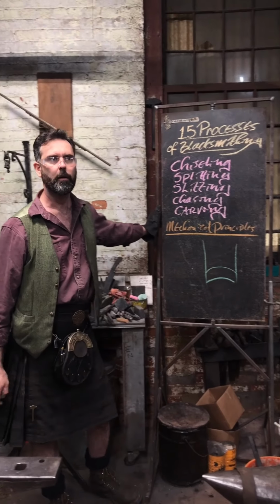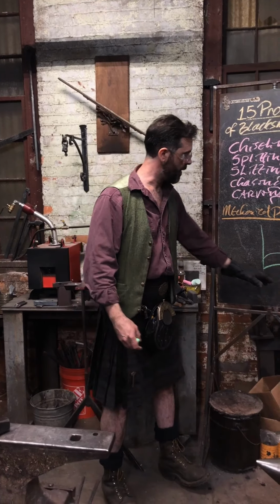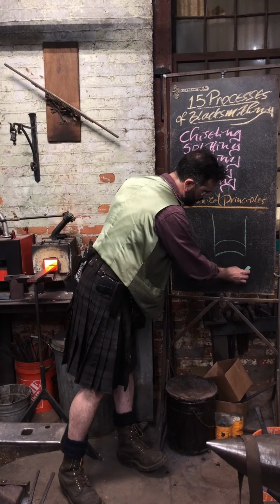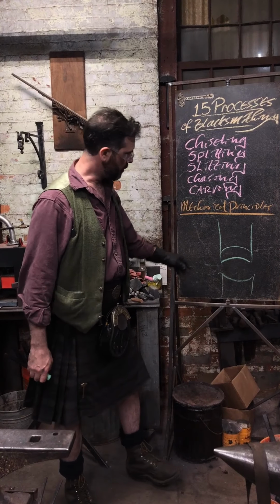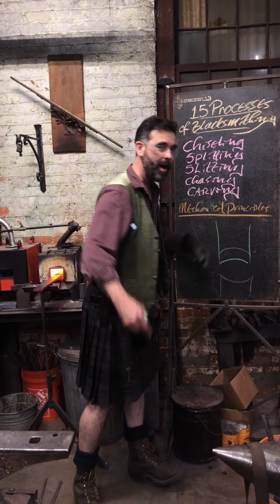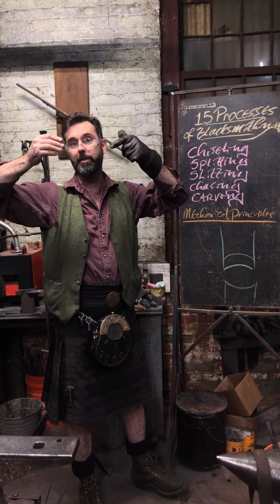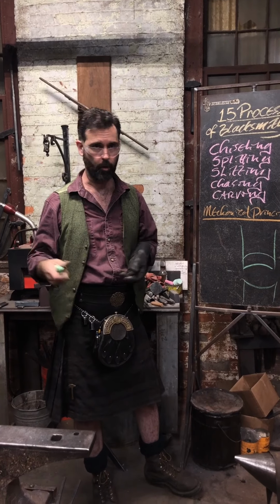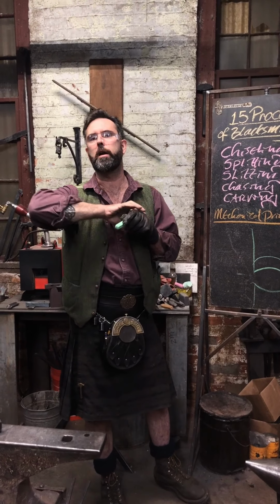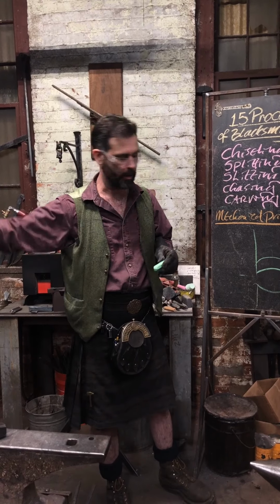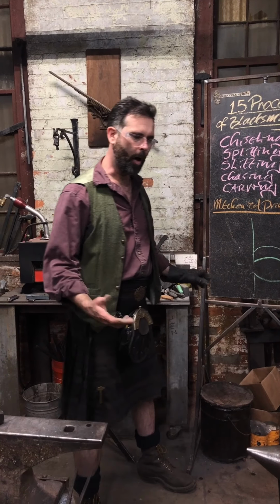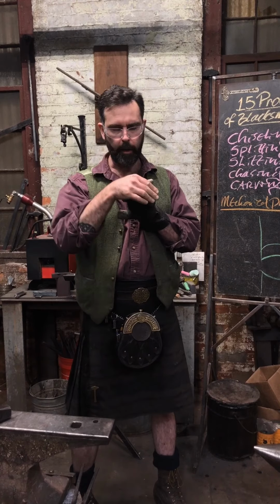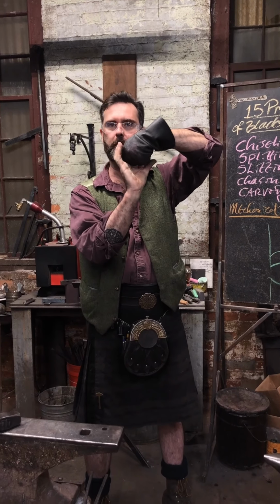And if you were cutting off bar stock, say with a bottom tool, which might have a slightly similar profile, you would come in, put your bar in there, and because it cut heavier on the outer edges, it would actually hold in better. So you can be very, very aggressive. It's a great way to chop off material quickly and efficiently when you're just trying to separate material. It doesn't have to be pretty, you're just trying to separate material, throw it out of the way. Where a radius tool this way, sure, it cuts up fast, but it's quite unstable. It doesn't hold the material, where a butcher will hold the material more stably.